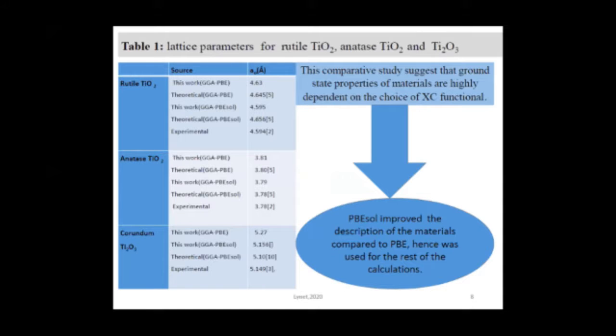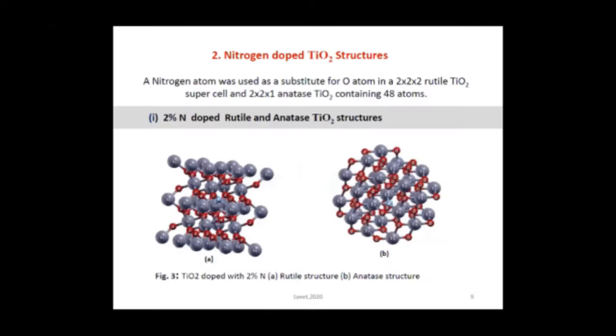So this comparative study suggested that the ground state properties of materials are highly dependent on the choice of exchange and correlation functional. And PBEsol proved to describe the materials better than PBE, so it was used for the rest of the calculations in this study. We then moved on to do doping. We used nitrogen as a dopant.